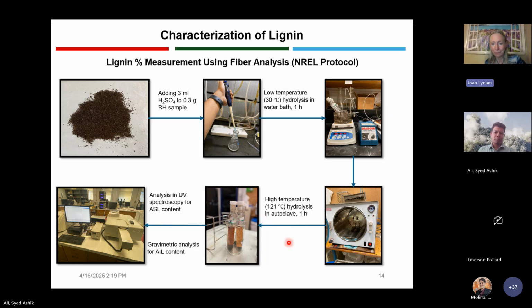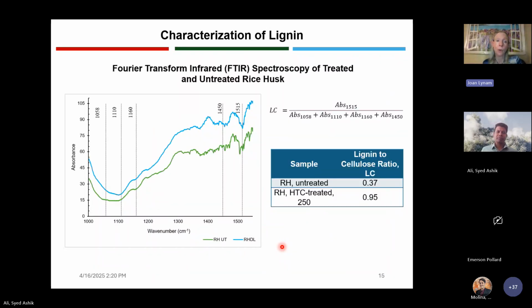We then did Fourier transform infrared spectroscopy of it, which can be a little hard to figure out. Well, gee, there's a squiggly line. How do you analyze this? We figure out the lignin to cellulose ratio. At the 1515 peak, you take the area of it and divide it by the areas of a number of other peaks, and that will give you the lignin to cellulose ratio. So that's how we analyzed it.